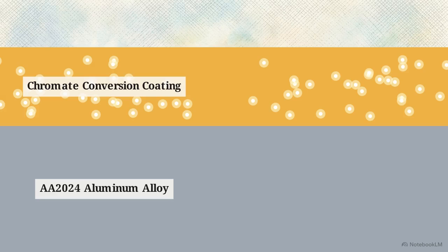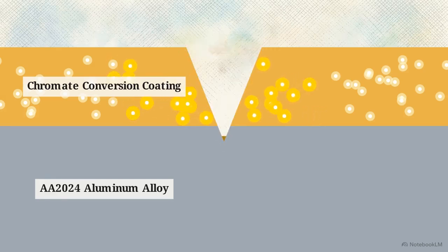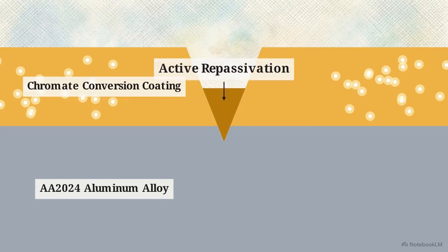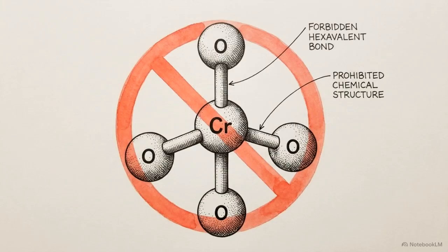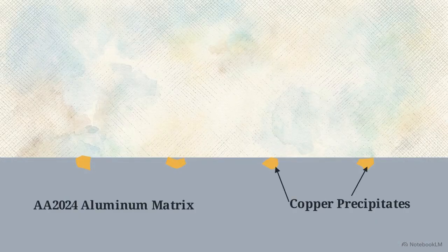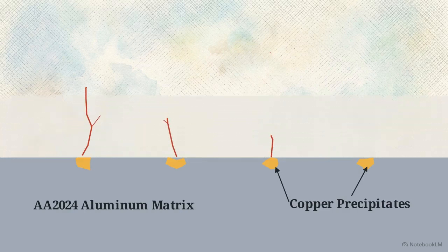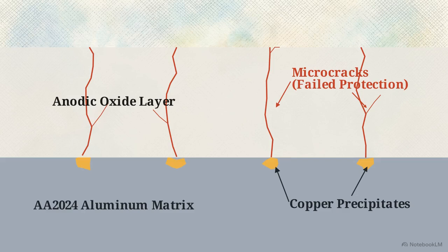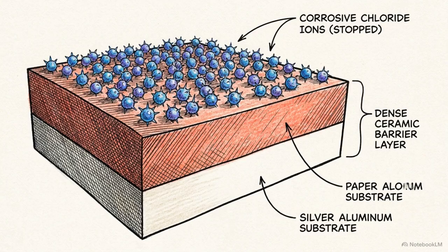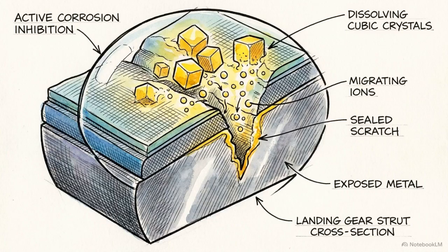Chromates provide active repassivation. They release ions that migrate across the metal surface to protect newly exposed or damaged areas. Modern REACH and RoHS mandates are now banning hexavalent chromium due to its toxicity and carcinogenic properties. Standard anodizing cannot solve this. Traditional oxide growth creates microcracks directly over the copper precipitates, leaving high-strength alloys unprotected. The solution requires moving beyond passive chemistry to architect a multi-layered hybrid electroceramic stack built from first principles. To succeed, this hybrid architecture must replicate the robust physical barrier and the active chemical defense of legacy chromates without the use of hazardous chemicals.